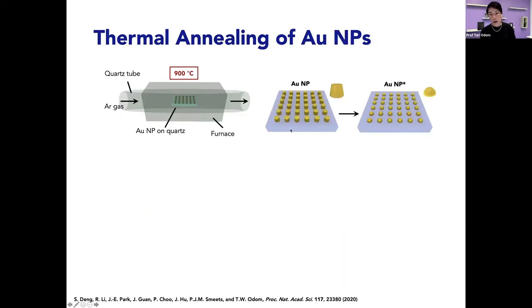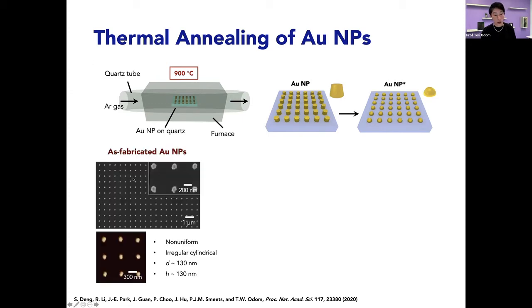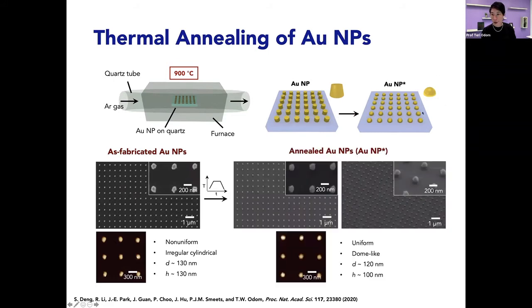And so of course the particle arrays look quite nice in the Blender scheme, but they're different as fabricated. For example, these as fabricated nanoparticles look pretty good, and the periodicity is perfect, but in terms of the individual shape, there is some variability because we're depositing through this hole array mask. So the idea is, can we thermally anneal these as fabricated particles with a specific temperature and time process? At the end of the process, we can reshape the particles so they reflow and then solidify to form these dome-like structures. And you can see just based on the tilted scanning electron micrograph that they look really, really nice.